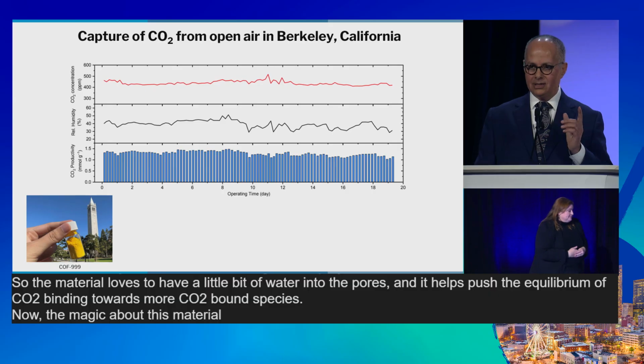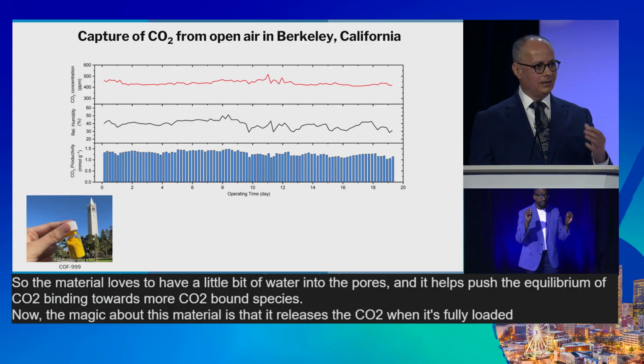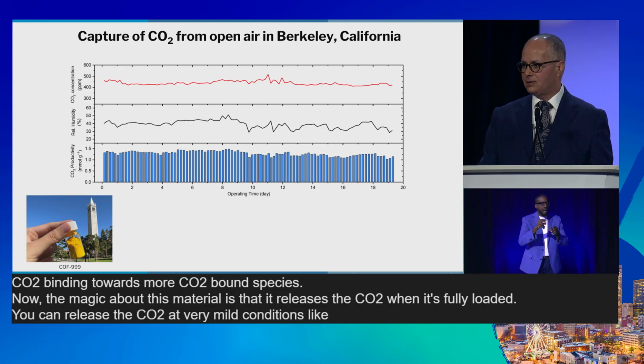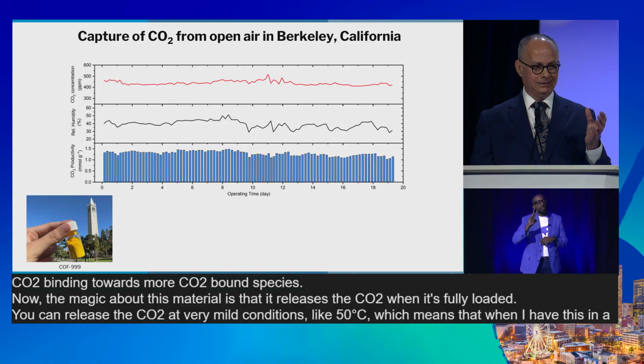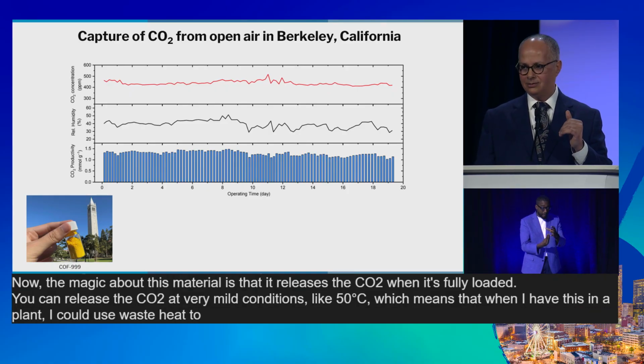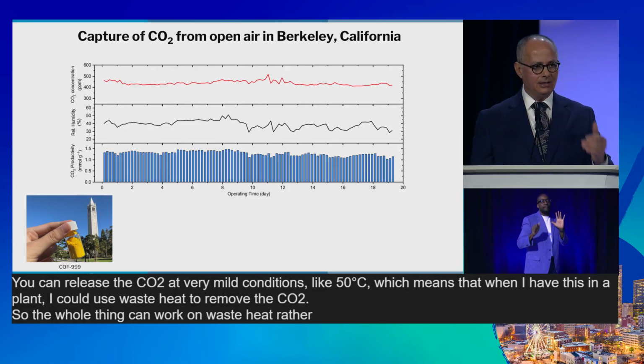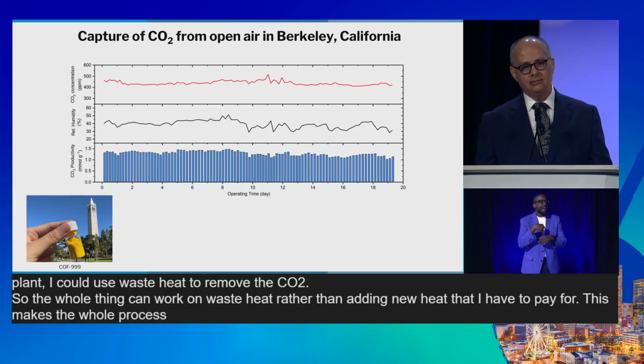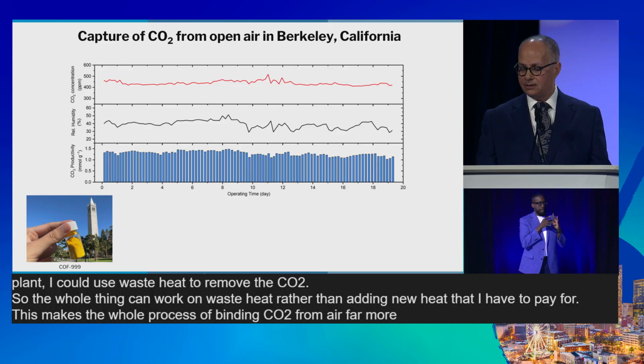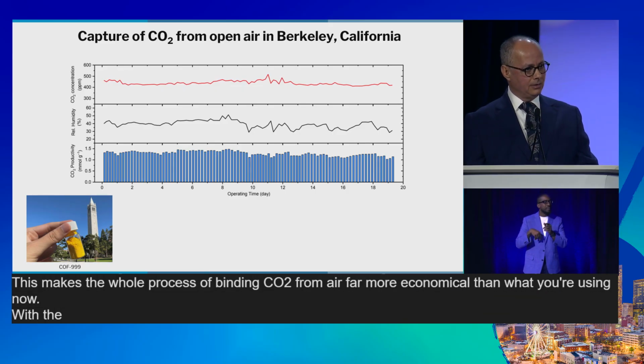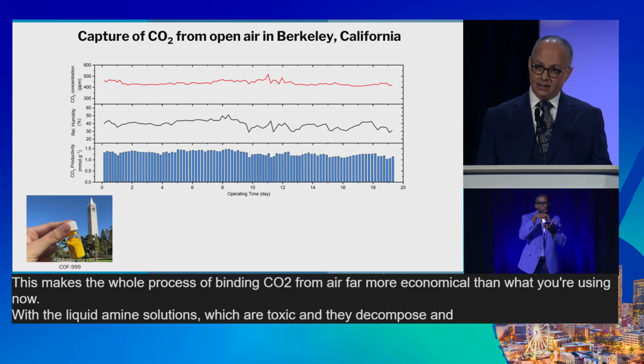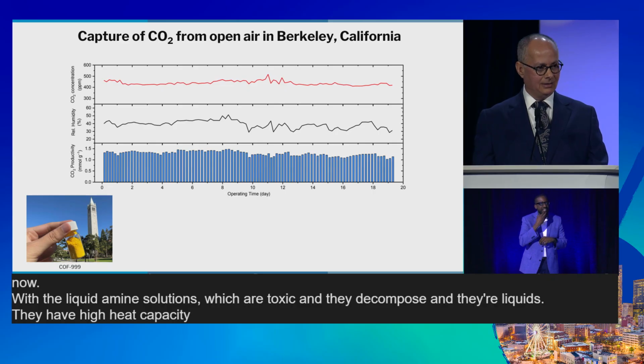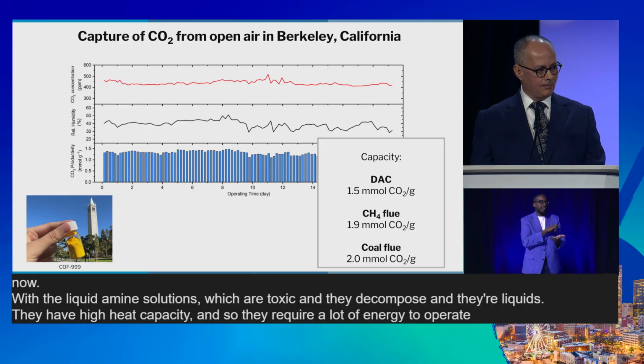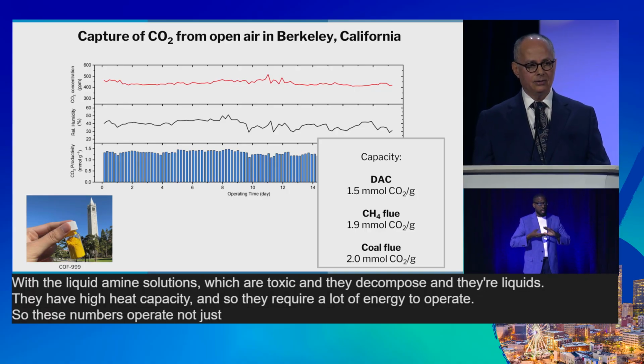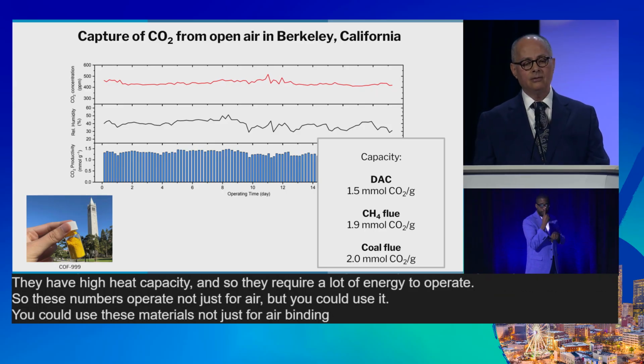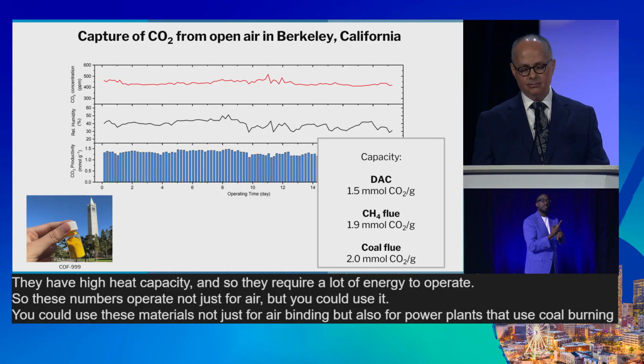Now the magic about this material is that it releases the CO2. When it's fully loaded, you can release the CO2 at very mild conditions, like 50 degrees Celsius. Which means that when I have this in a plant, I could use waste heat to remove the CO2. So the whole thing can work on waste heat rather than adding new heat that I have to pay for. This makes the whole process of capturing CO2 from air far more economical than what you're using now with the liquid amine solutions, which are toxic and decompose, and being liquids, they have high heat capacity, and so they require a lot of energy to operate. You could use these materials not just for air capture, but also for power plants that burn coal or natural gas.